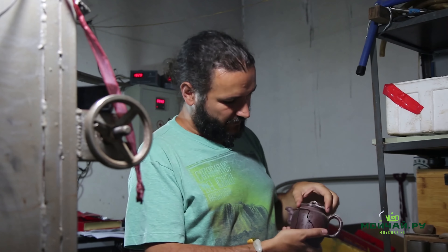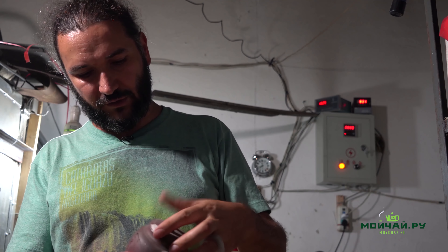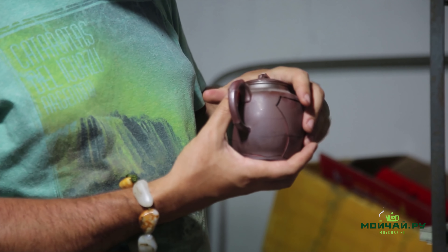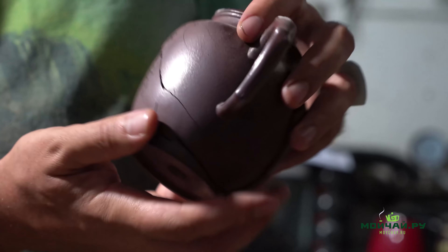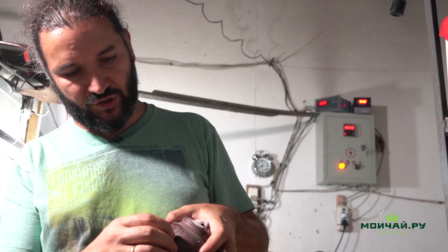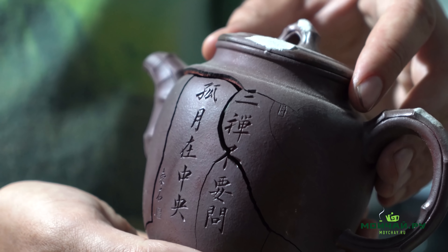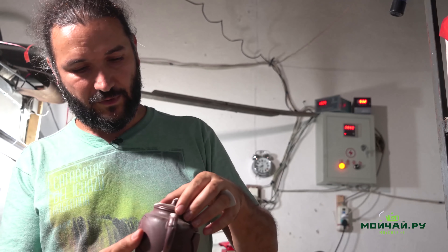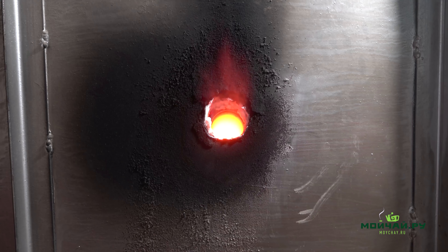When we came in the morning, he hadn't taken the pottery he was working on since yesterday from the kiln — that's what can happen with teapots during the firing process. It's absolutely unpredictable. This teapot was well made, everything was perfect, there were no bubbles, but he misjudged the temperature and many teapots were spoiled. We can see how the temperature affected the teapot — the clay turned black to the middle of the walls in some places, while it kept the original color of Zhuni inside. It's baked to the middle thanks to the wood-firing process. It makes wood-fired pottery more expensive — it's always an experiment. You put 20 teapots in the kiln and only 5 survive.